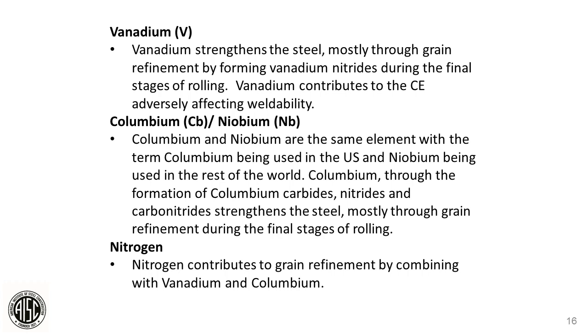Now, vanadium, columbium, and nitrogen, we bring those up together because they're all tied together. These are called microalloys. Vanadium strengthens steel mostly through grain refinement by making vanadium nitrides. They precipitate out when the steel is rolled. And it also counts against your CE. Columbium, niobium, same element. We typically use columbium as a term here in the United States, but it makes columbium carbides and nitrides, and again, it affects the final grain size of the steel after rolling. Now, nitrogen is an element that's just dissolved into the steel from the air, atmosphere, and it's used in combination. That's what vanadium grabs a hold of. That's what columbium grabs a hold of. They'll combine with that to make the nitride, which precipitates to the grain boundary, which makes the fine grain steel. Next slide.